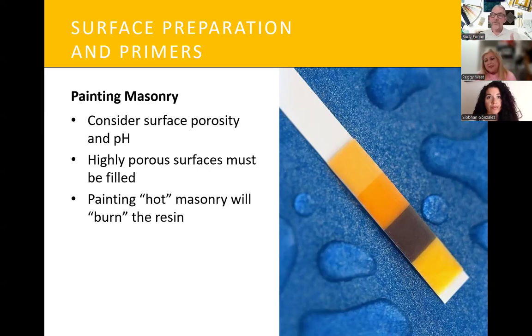Now, what happens is when you put paint on top of something like that, all latex paints will allow moisture to come through, but the permeability or the breathability of the latex paint will not allow those crystalline salts to pass through. So they will collect behind the coating itself, and that's what we call hot masonry. And that alkali, if it's laid up against the latex resin, or pretty much any kind of paint that you use, will burn that resin. It will make that resin fall apart.